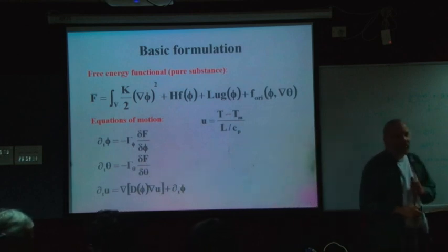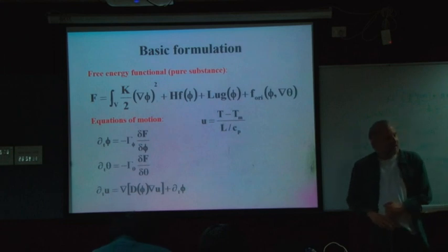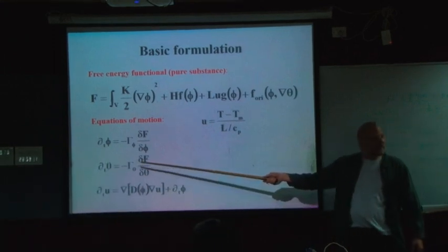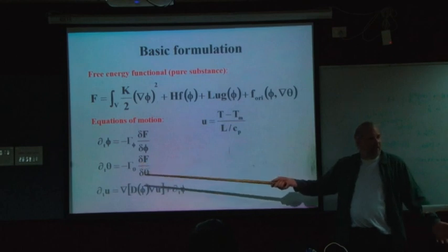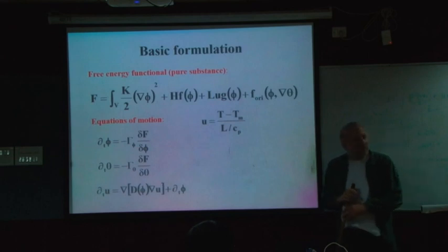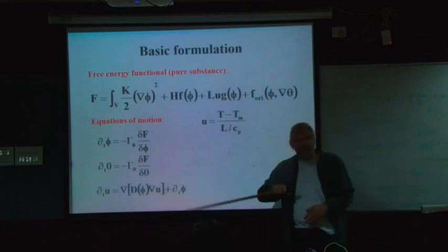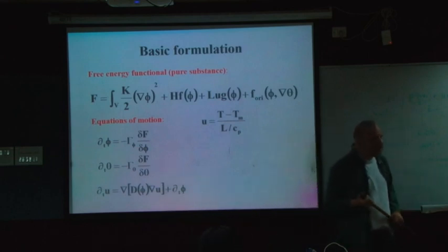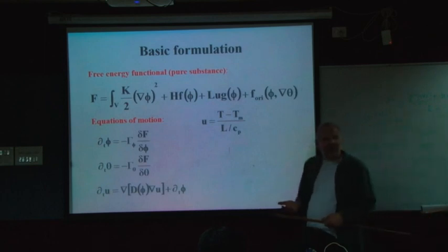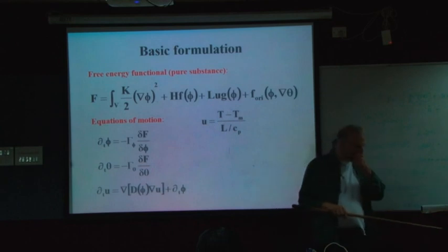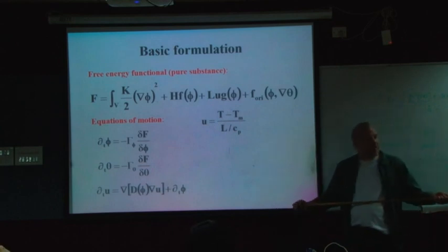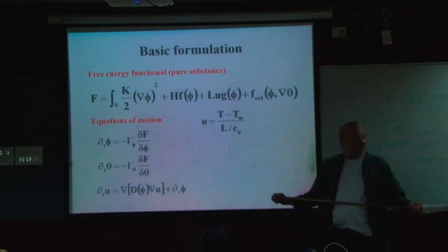Now, everybody involved in the field that has developed these models agrees that this equation is wrong, in the sense that the orientation doesn't just obey a relaxation equation. It has some geometrical constraints that are not respected by this equation. Still, it does a reasonably good job, because it ensures local equilibrium between grain boundaries. It enforces the right local equilibrium law at the trijunction point. So for the moment, nothing better is in sight.